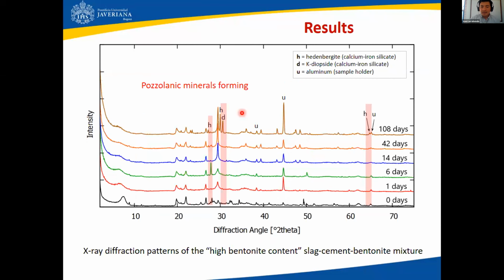For the spiked sample, for the high bentonite content sample, what is interesting is that we did confirm the presence of new pozzolanic minerals, and you can see the evolution of them with time.